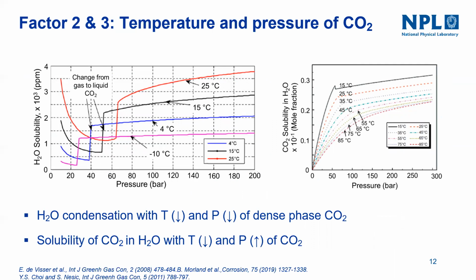If the corrosion testing is happening at 25 degrees centigrade, and the temperature suddenly falls during the testing to 15 degrees centigrade, there is a decrease in the solubility of the water, which is like 500 ppm. So if you are very close to the solubility limit, a fluctuation during the testing can cause accidental condensation of the water, where the corrosion can take place.